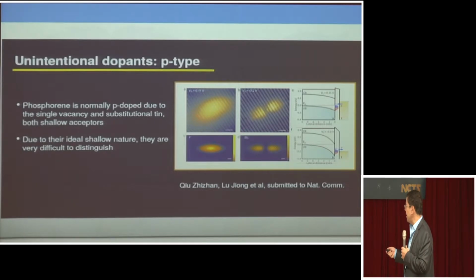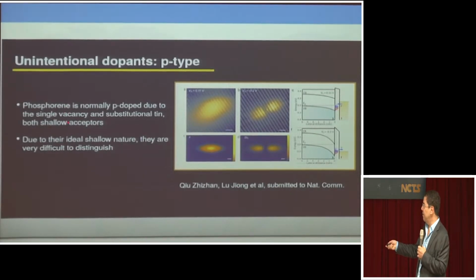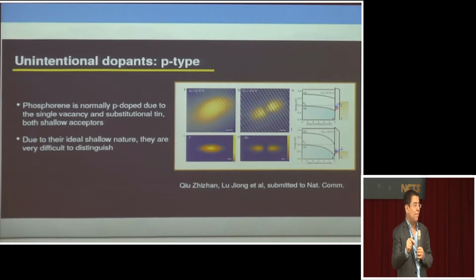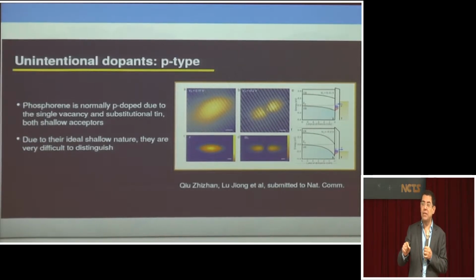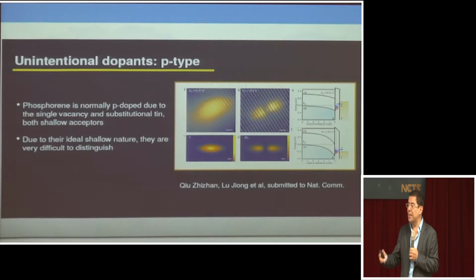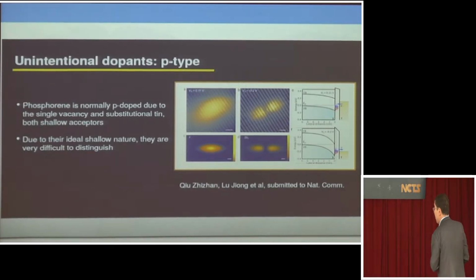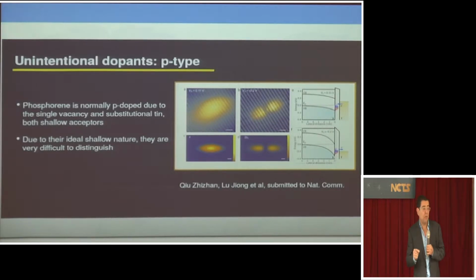For instance, in this case, this is actually STM data from Lu Jiong's group at NUS on some defects that are found in phosphorene. Okay? And this is the numerical simulation, which we believe is coming from either vacancies or tin. Sometimes you can have these atoms there. Depending on how you produce the black phosphorus crystal, you may have some of these atoms there. So again, it goes back to the semiconductor industry, understanding different types of defects that can be created. The nice thing is that you can really probe them using, for instance, STM. It's very easy to probe these things.